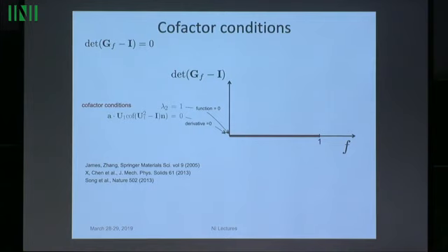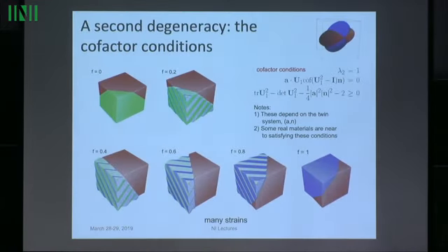Now, of course, at every point in here, a middle eigenvalue of GF is 1. An eigenvalue of GF is 1. We also have an inequality. And if we want every single point along here, the eigenvalue which is 1, to be the middle one, you have to satisfy that inequality. Necessary and sufficient. Okay, very good. Okay, so here's what it looks like. So any volume fraction satisfies the crystallographic theory.